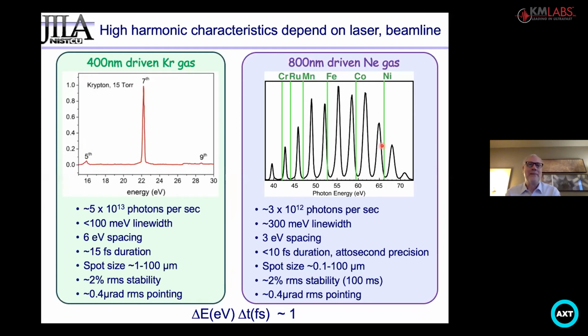Here are some examples of the performance of the system. You can actually take the laser, which is an ultra-fast titanium sapphire laser, and use that output directly to get a comb of harmonics with relatively broad spectral bandwidth for each harmonic. So you would use a simple monochromator to isolate a single harmonic peak.